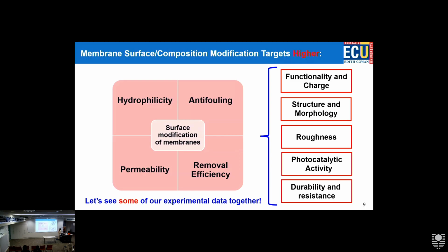So we need to play around in terms of the feed solution that comes into contact with the membranes, basically. So we need to change the structure and morphology. We can play with the thickness of the membrane, we can play with the porosity of the membrane, and so on. We want the roughness to be less in terms of the fouling. Roughness, do you know what is roughness? With roughness in terms of membranes, we have more ridge valleys and we have more surface area, basically. So if we have more surface area, we expect to have more surface contact for water. So with higher roughness, we have better efficiency in terms of the water production, but we have higher fouling tendency, because those foulants can easily get attached within the ridge valleys and then create aggravated fouling.